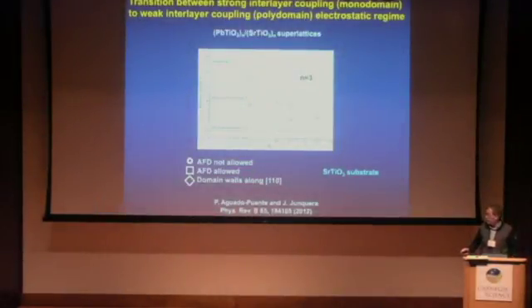So a few years ago, we started to do some first principle calculations in these lead titanate, strontium titanate superlattices, and essentially we were able to corroborate all these arguments. In particular, for a periodicity of 3 unit cells of lead titanate and 3 unit cells of strontium titanate, the ground state was monodomain, with the polarization pointing in this R phase, essentially along the 111 direction, while the domain structure here, we were able to stabilize only as metastable phases.